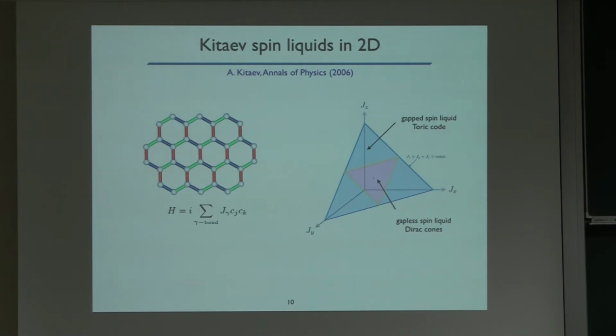And this gapped spin liquid is actually in the same topological phase as a toric code model. If all the coupling constants are approximately the same, then we're in this magenta region here in the middle, and that is a gapless spin liquid. And what that means is that the Majorana fermions have a gapless dispersion, and in this case it's the same dispersion as you find in graphene. So you have the Dirac cones that sit at the corners of the Brillouin zone.